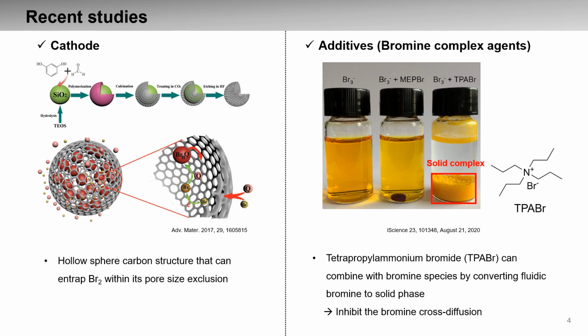Many studies have been reported on cathode materials where the bromine reaction occurs. The main point is that the bromine species can be entrapped in a porous carbon electrode. In this paper, they synthesized a hollow sphere carbon structure by using a silicon oxide substrate, calcination, and CO2 activation. So it can entrap the Br2 within each pore by size exclusion, with a pore size of 1 to 2 nanometers.